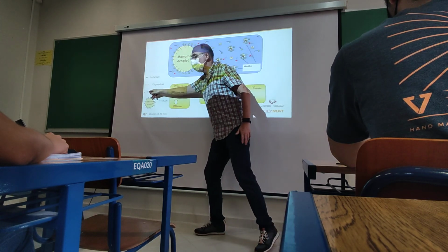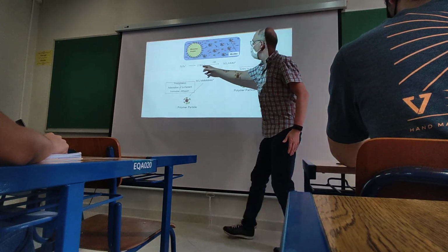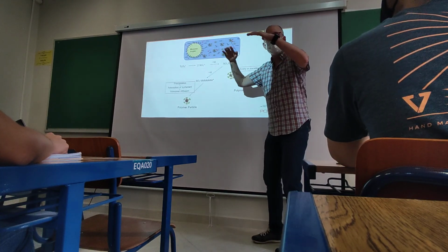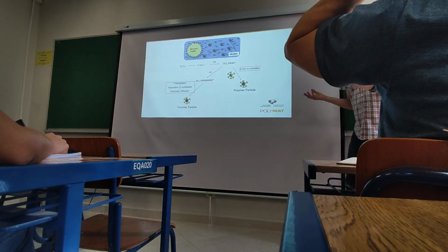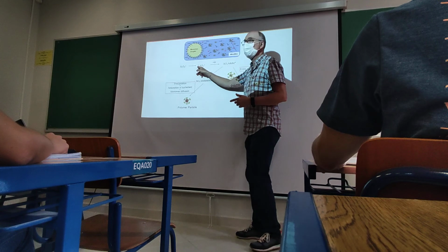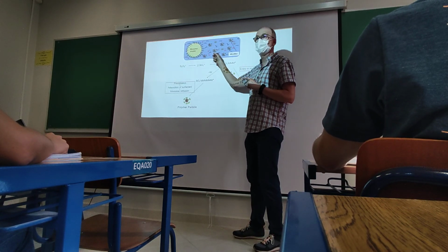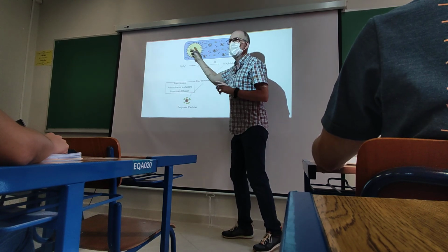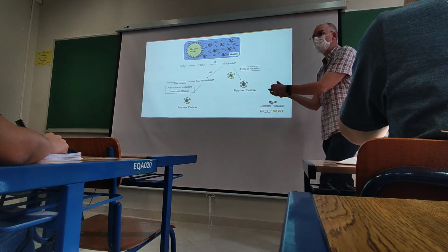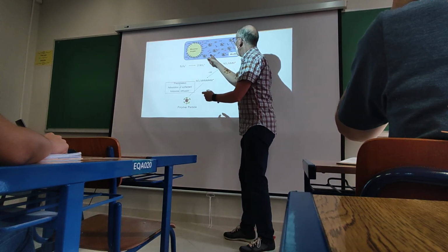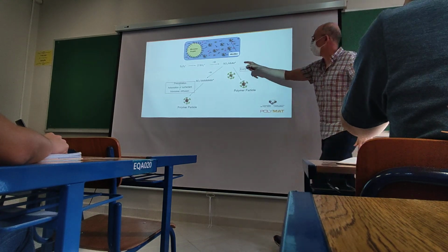So, under these circumstances, now, what happens? The radicals that we generate thermally, by temperature, these radicals are water soluble, they are in the water phase. So they will find the monomer in the aqueous phase, because the radicals will not enter into hydrophobic surfaces, because they are very hydrophilic. So they are water soluble. So these radicals will find monomer in the aqueous phase and will react with the monomer in the aqueous phase.